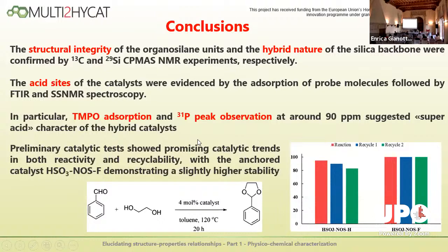As already Urbano told, these materials are promising in first preliminary catalytic test. In particular, the fluorinated compound demonstrated a slightly higher stability upon recycle, and maybe this is due to the slightly higher acidity character, as well as the higher thermal stability.